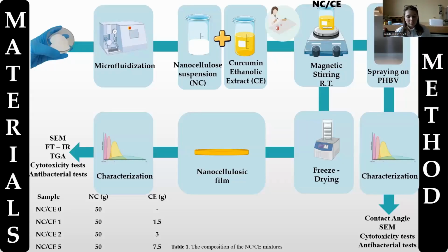We started with the microfluidization of microcrystalline nanocellulose and obtained a suspension which was mixed with curcumin extract in different ratios as stated in table 1 below. The mixtures were kept under magnetic stirring at room temperature, and a part of each of these mixtures was freeze-dried for characterization by FTIR, SEM, cytotoxicity, and antibacterial tests, while another part was used for spraying on the PHBV film, which was as well characterized by contact angle, cytotoxicity and antibacterial tests.